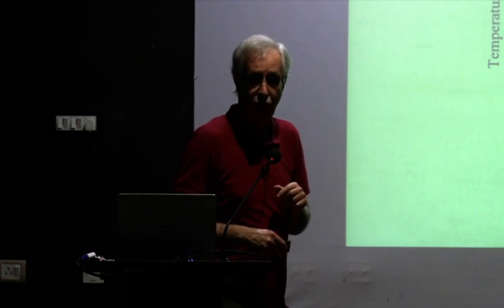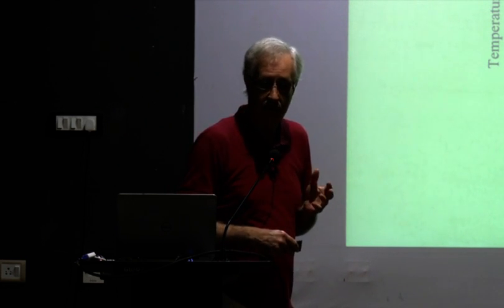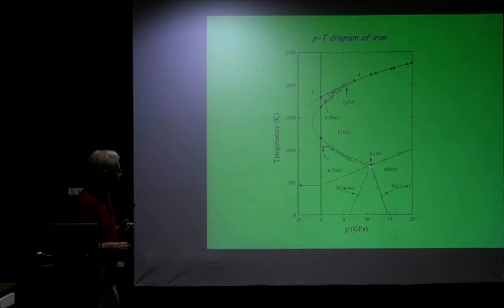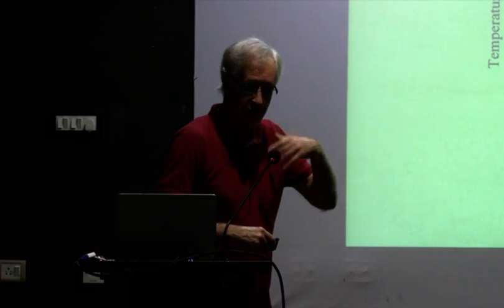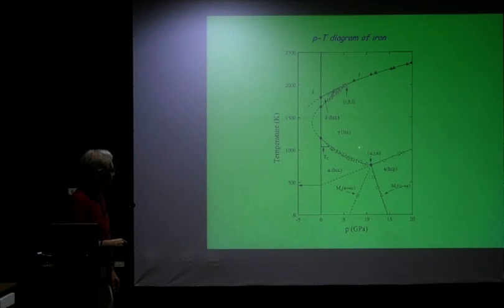Now, there are certain things that we can learn from this phase diagram. This tells us what's happening under pressure, good, but what have we learned so far? If you take this line over here, which is the transformation line between the FCC and the hexagonal state, and you extrapolate this back to 0, you would see that an epsilon FCC transition would occur at around this temperature over here, close to 500 Kelvin. Meaning that if it were possible to stabilize the epsilon state, it would have had a transition temperature of so much, and the epsilon phase would have been more stable with respect to the FCC phase.